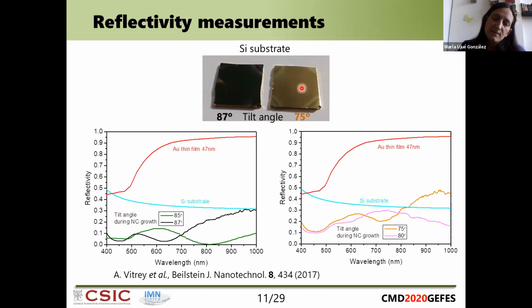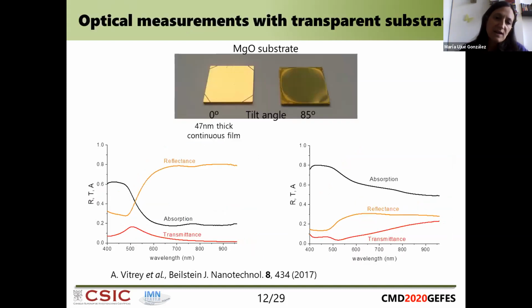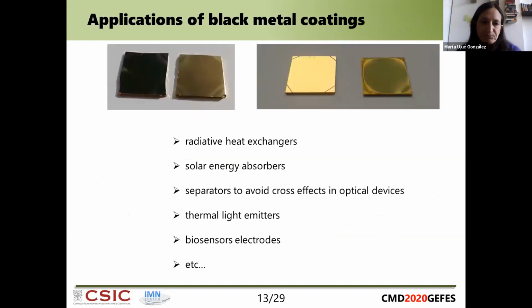And in this case, because the nanocolumns are more homogeneous, and also more homogeneous in height, we don't have as high light trapping, it is not as efficient here. And well, we checked that this was not depending on always having the silicon substrate. We could also have obtained the same kind of dark behavior with a high angle on a transparent substrate, just in case we need it. And well, this is a very, very simple way of obtaining a black metal coating that can be used in several applications in order to get heat exchangers, absorbers, and these kinds of things.